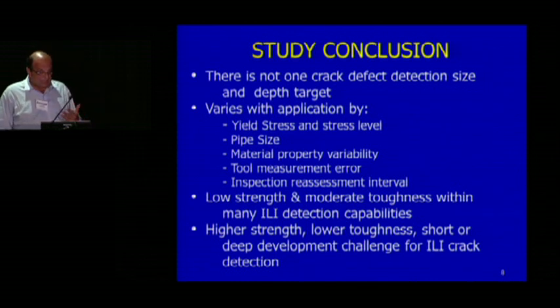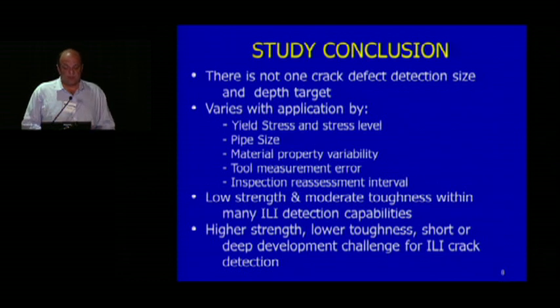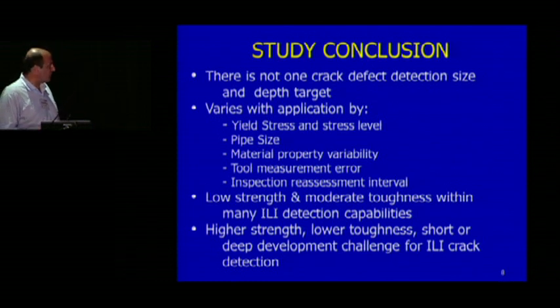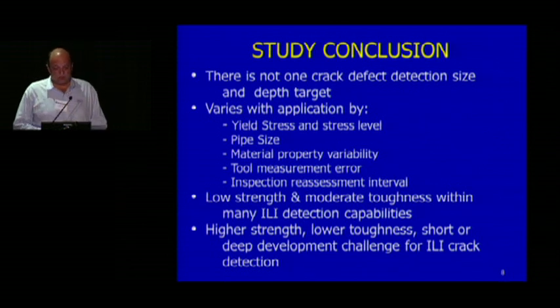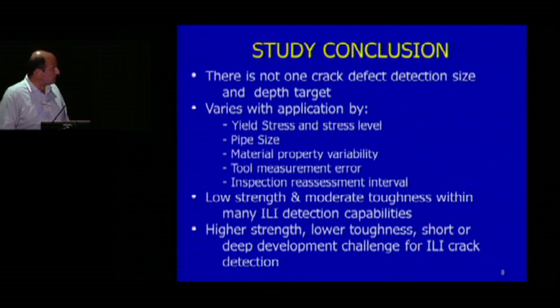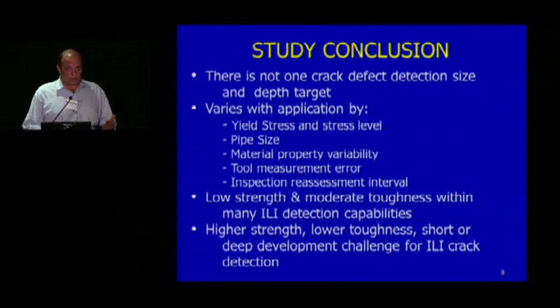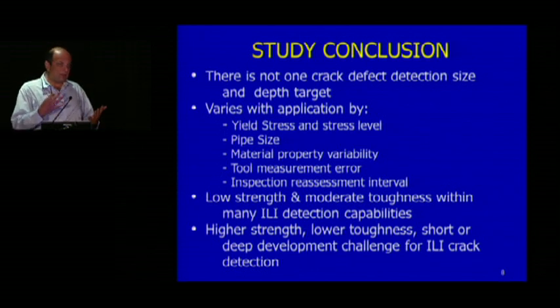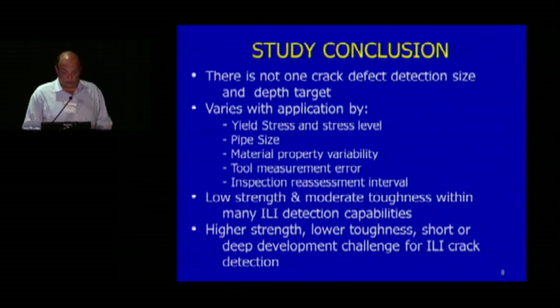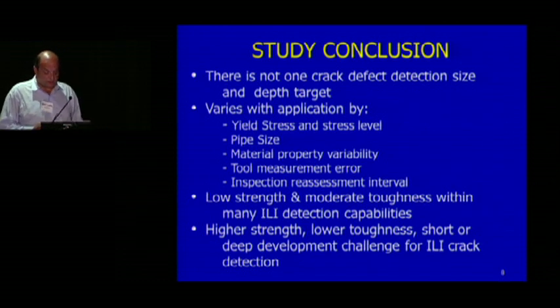So at the end of the study, again, it was very comprehensive. Basically, we don't have one crack defect detection size for all cases, as you would expect. So it varies by yield stress and stress level of the material, the pipe size, how much material property variability you have, and obviously your tool measurement error. But we have been able to put all this together, and for any particular combination of those parameters, we have a minimum defect size that you have to have detected in order to have something equivalent to a hydro test.